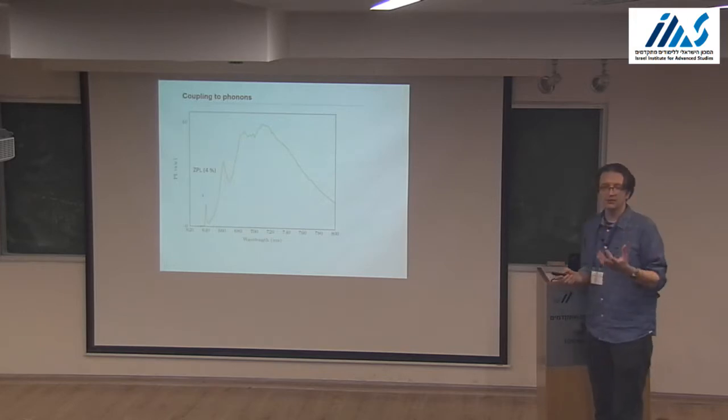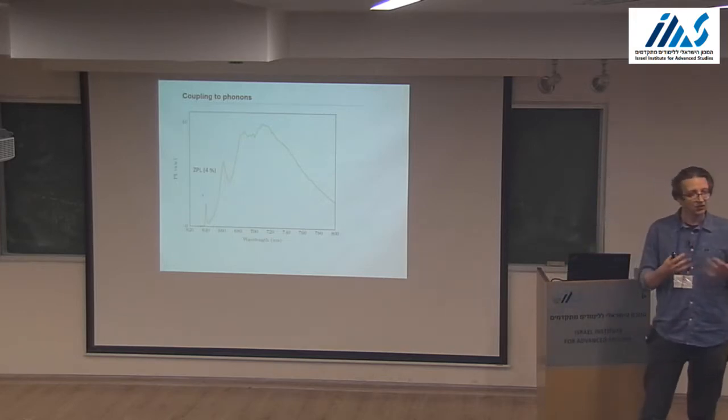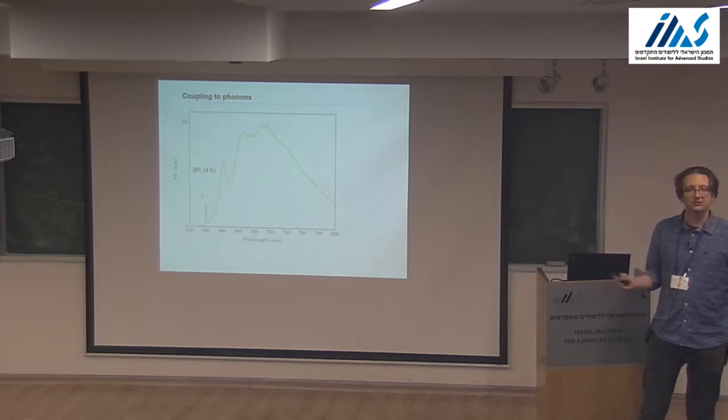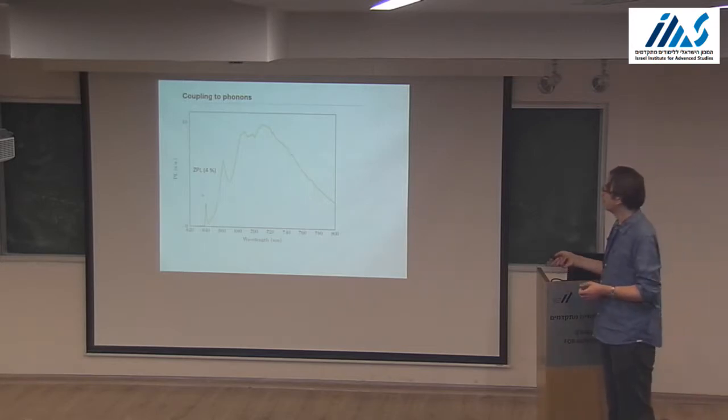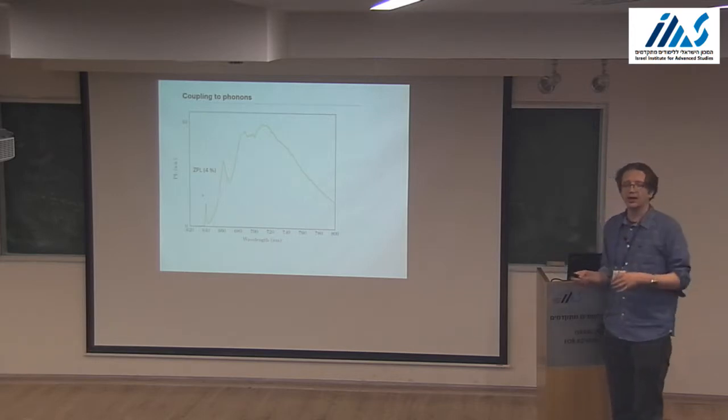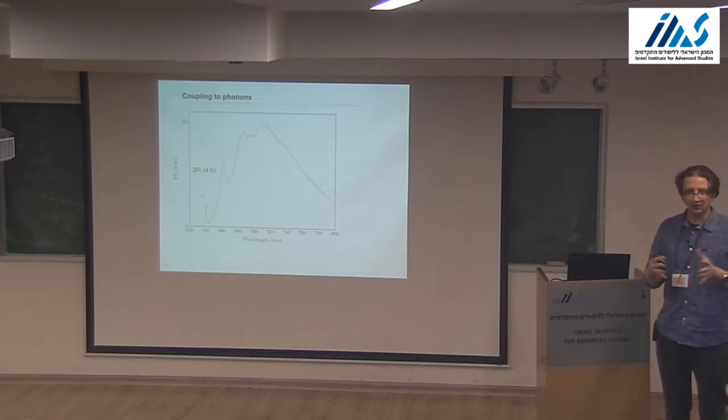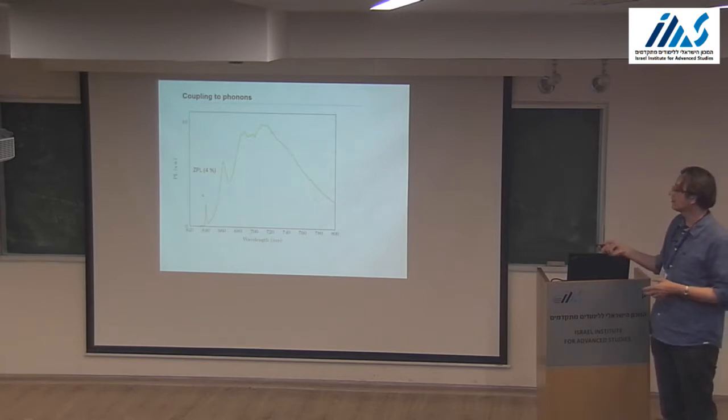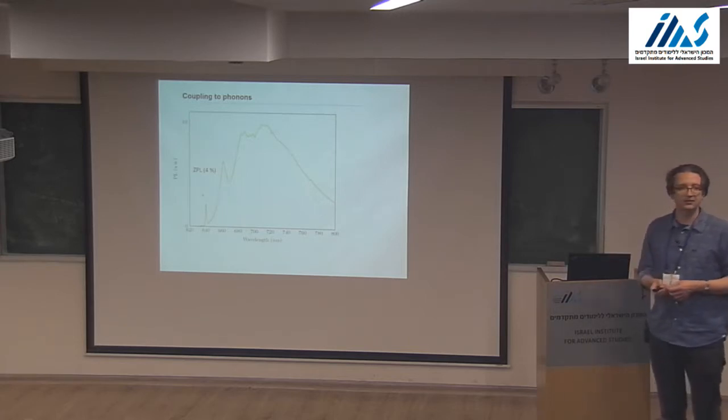These are the photons that do not get any imprint of the quantum state in the diamond lattice, so they can be used for long-distance quantum communication, and then there is a very strong phonon sideband. This is emission of a photon by the atom with excitation of lattice vibrations, and those are not very useful in this business.